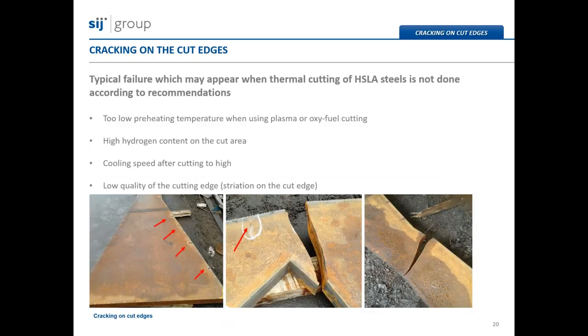In the next part of the webinar, we also have to say something about typical failures on the cut edges. Cracking is, I think, the most frequently detected failure when thermal cutting of high strength, low alloy steels of high thickness is not done according to the manufacturer's recommendations. The producers of high strength, low alloy steel, like construction or wear resistant steel grades, would like to inform the final users about this major failure.